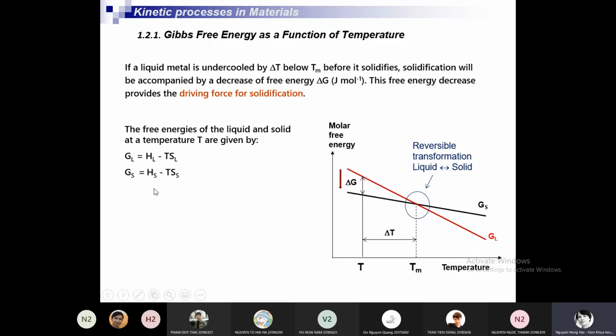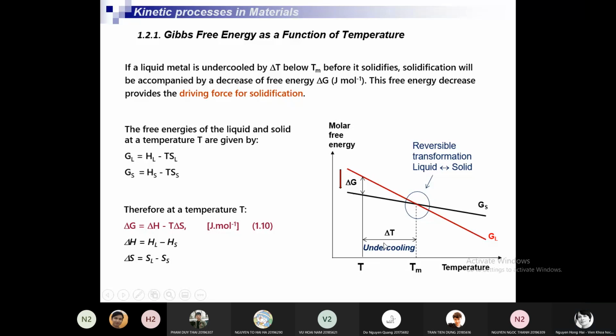This comes from the free energy equation. So at temperature T, delta G is equal to delta H minus T delta S, where delta S is the entropy of liquid minus the entropy of solid. This is the driving force for solidification, and you can see the driving force for solidification is proportional to undercooling. The greater the undercooling, the greater delta G, the greater the driving force.